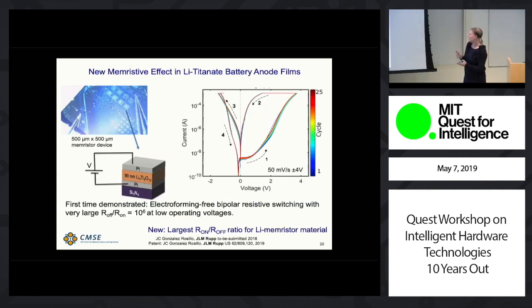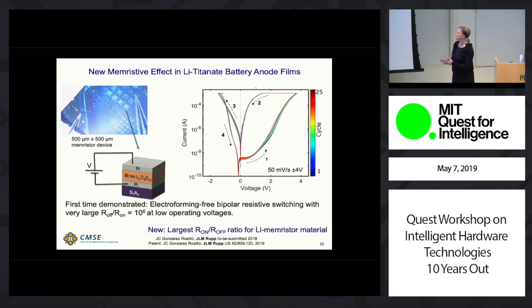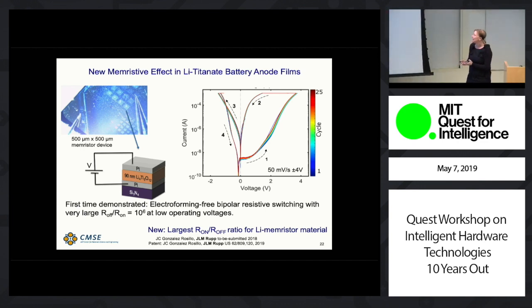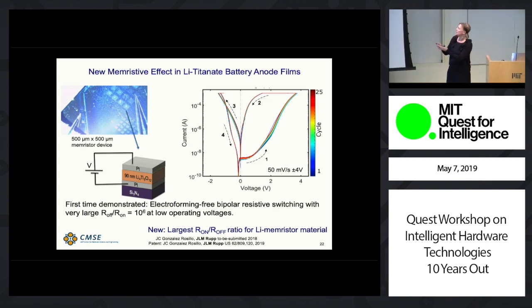And the really cool thing I'm excited to show you is that this lithium titanate can actually be used as a memristor. So this is a hysteretic current-voltage profile. You can cycle that hundreds of times. And the interesting thing is that you can obtain huge resistance on-off ratios for this lithium titanate material.